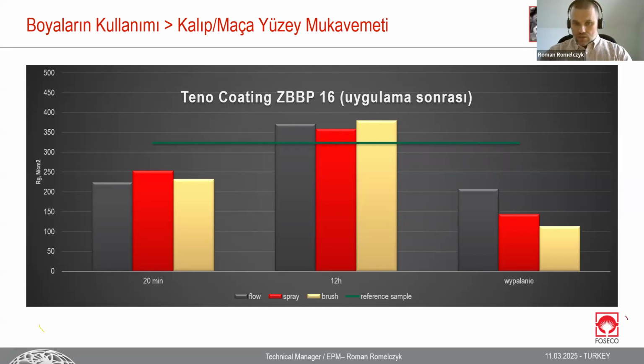When we talk about 12 hours drying at ambient temperature, alcohol has a chance to evaporate. The jelly form of binders, we can say, goes back to the normal one. And why is it more than the green one? Because the curing process has a chance to finish. For the curing process, we can say 24 hours is a full process of curing. When we talk about alkaline phenolic, furans, or PUCB, we count like that when we research anything. So here we can see that the curing process has a chance to finish, and what was destroyed by alcohol can grow up again.